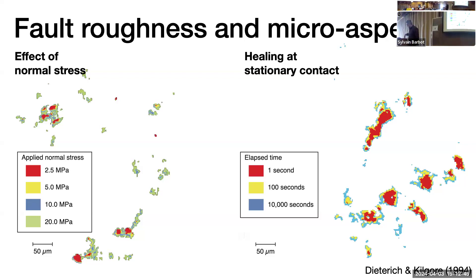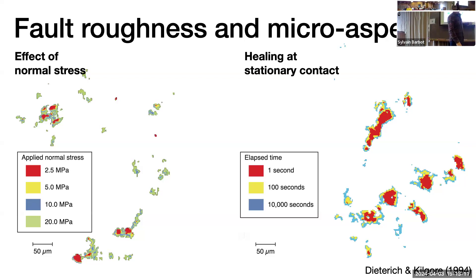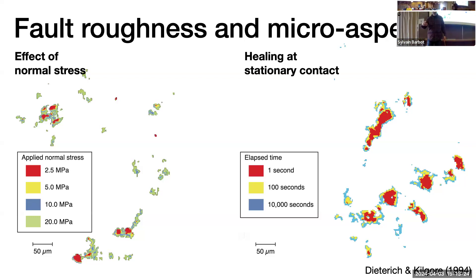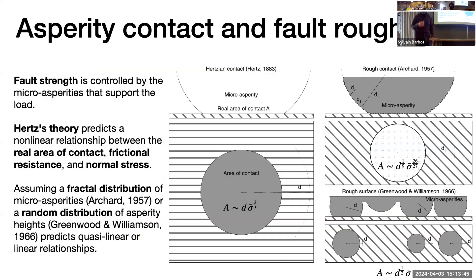As you increase normal stress, you increase both the population of contacts and their size — intuitive, since pressing on anything collapses it into its own shape. We call this compaction creep. But wonderfully, if you do this at any stress and wait — one second, ten seconds, an hour, three days — the contact size will not be the same. The contacts collapse under their own weight and become flatter and flatter over time. So micro-asperities have a strong dependence on normal stress, but they also evolve spontaneously as a function of time. There is a time component to the strength of contacts. This is well understood from the lab but hasn't been translated into a predictive relationship — that's what we'll do now.